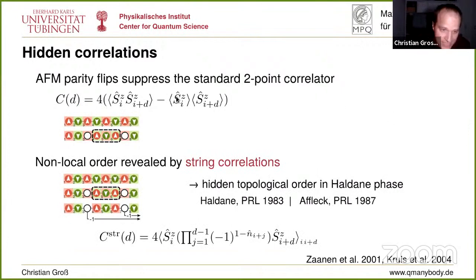But there's a way of revealing this. And the way of revealing is by using non-local string correlations. Because you know what the hole does, it just flips all the spins that come after the hole. So what I can do is measure a string correlator that goes through all the chains. And since we have full counting statistics, we can do that in post-analysis and take each hole into account with a -1, flipping the spin alignment that we expect after the hole once upside down. And with this, we can take those holes into account and try to recover the spin order.